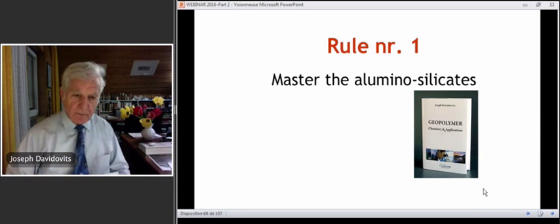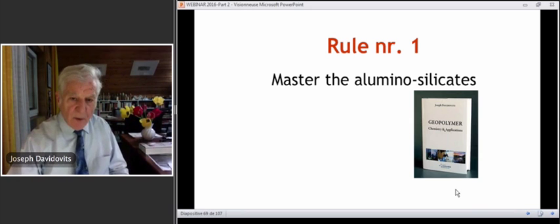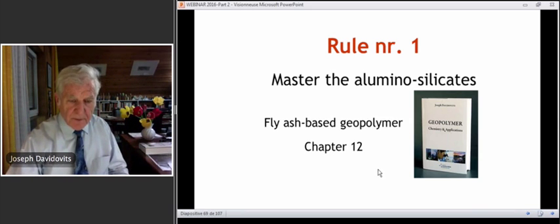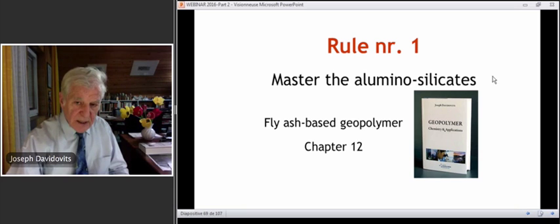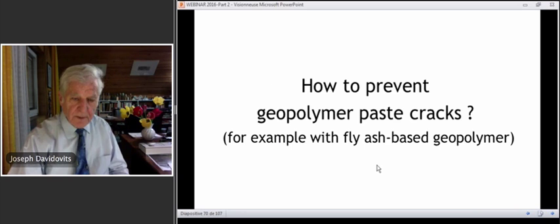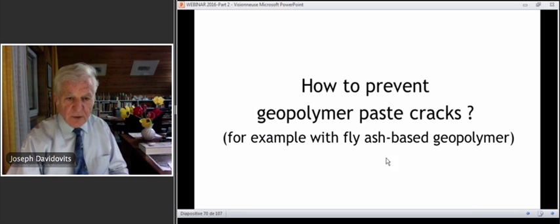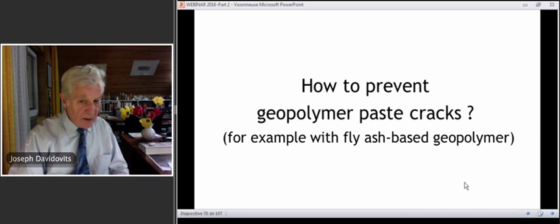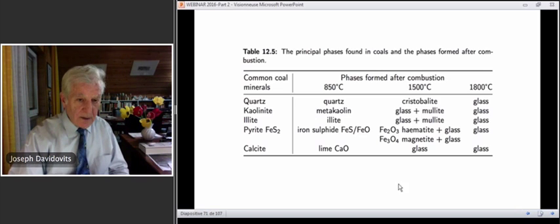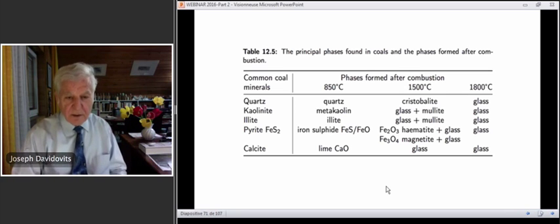So, rule number 1, master the aluminosilicates. I am always repeating the same. For example, if we take fly ash-based geopolymer, chapter 12, master the aluminosilicate means you must know what you have, what type of minerals you have in your aluminosilicates. For example, I had this question: how to prevent geopolymer from cracking, for example with fly ash-based geopolymer. It is obvious that the answer relies on your knowledge about what a fly ash is. So you have to know what you have here in terms of principal mineral phases.